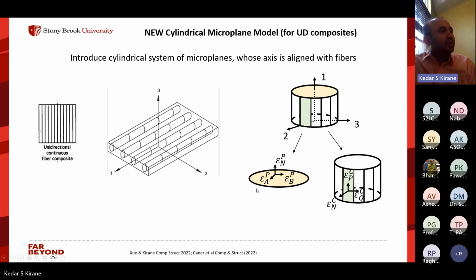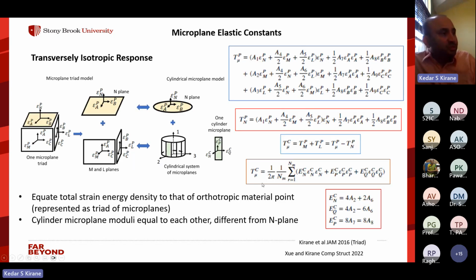So then what we do is, instead of the principle of virtual work, we define the strain energy density at a point. And this can be done by introducing three mutually perpendicular microplanes at that point instead of many, just three mutually perpendicular ones. And we can show that the entire strain energy density of a transversely isotropic material can be represented by three microplanes. So we showed this in a 2016 Journal of Applied Mechanics paper, where we developed this so-called microplane triad model. So this is called the microplane triad, three mutually perpendicular microplanes.